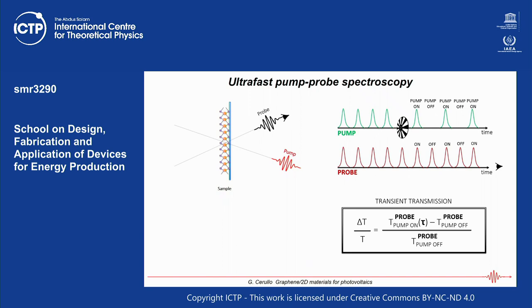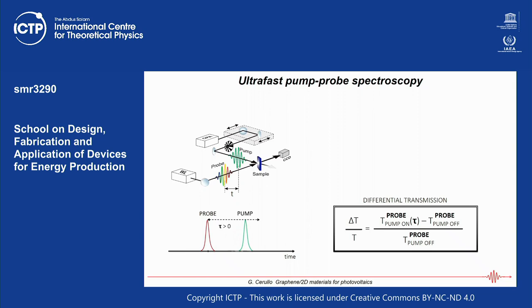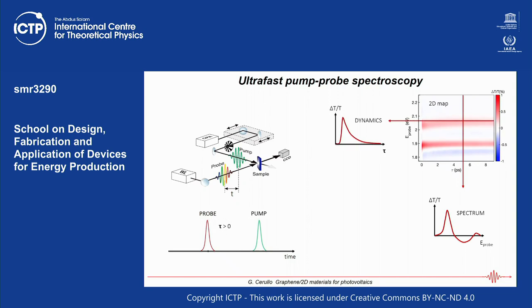In practice, you have a sequence of pump and probe pulses, and with a chopper you switch the pump on and off, measuring probe transmission with and without the pump. By moving the delay with a mechanical delay line, you get a map: the time delay on one axis and the transmission spectrum of the probe as a function of frequency on the other. You can take a cut at a given delay to get a spectrum, or a cut at a given frequency to get dynamics — a very powerful technique that gives very rich information.